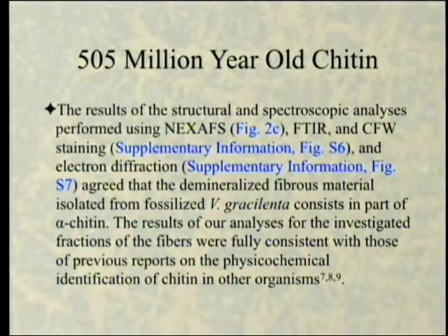The results of the structural and spectroscopic analyses performed using NEXAFS and FTIR and CFW staining and electron diffraction agreed that the demineralized fibrous material isolated from fossilized V. gracilenta consists in part of alpha chitin. The results of our analysis for the investigated fractions of the fibers were fully consistent with those of previous reports on the physical chemical identification of chitin in other organisms.